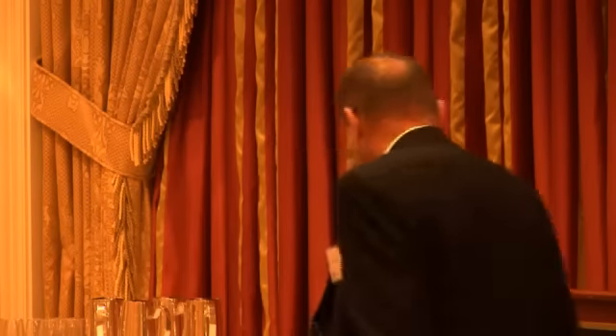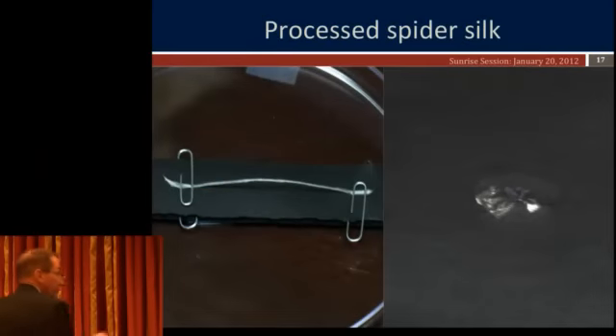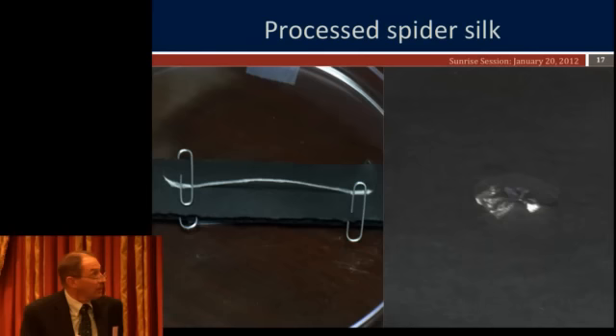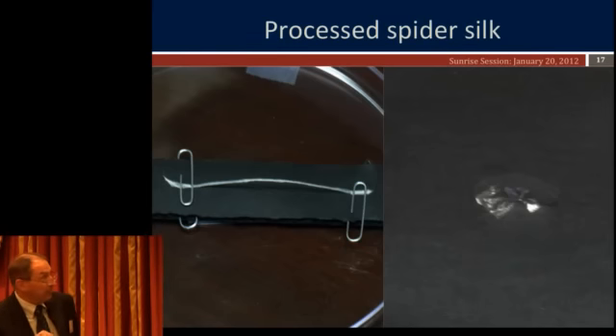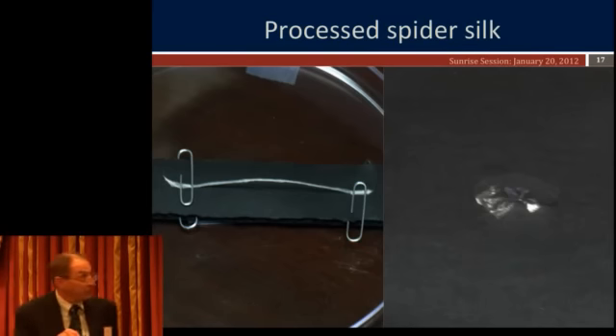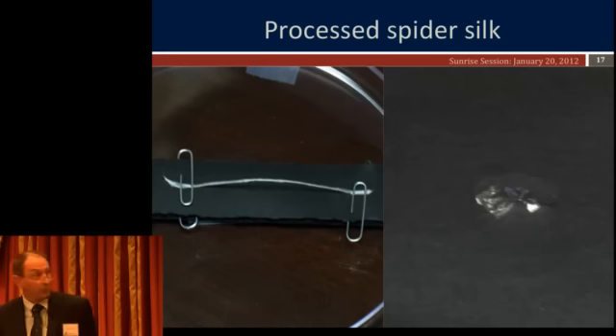So this, just to give you an idea, is actually 100 strands of the fiber. The finest fibers we make are about 5 microns in diameter. That's 100 fibers together. That would be plenty right there to use for an artificial ligament. That has plenty of strength right there to substitute for any ligament in your body.